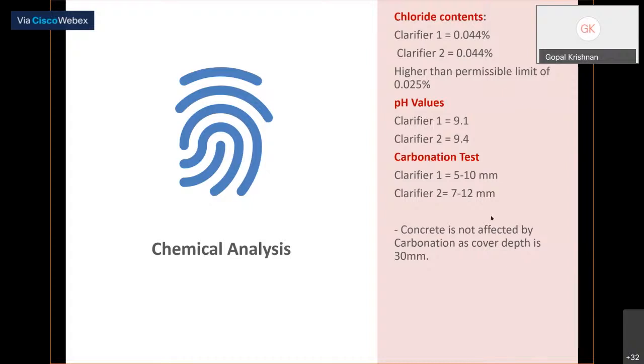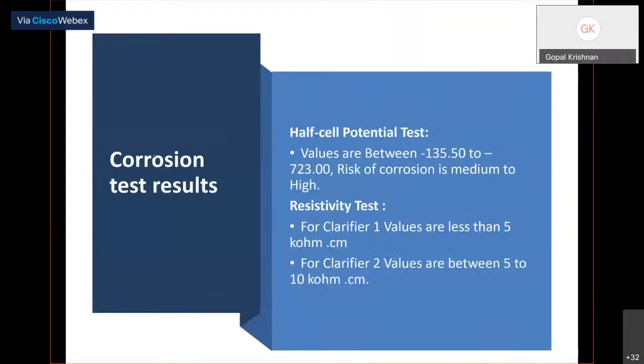But where the problem is, the half-cell potential is showing high risk, medium to high, with readings of minus 135 to minus 723 millivolt. The resistivity also shows inadequate. Corrosion is happening. So these two things indicate high corrosion probability because of the resistivity.